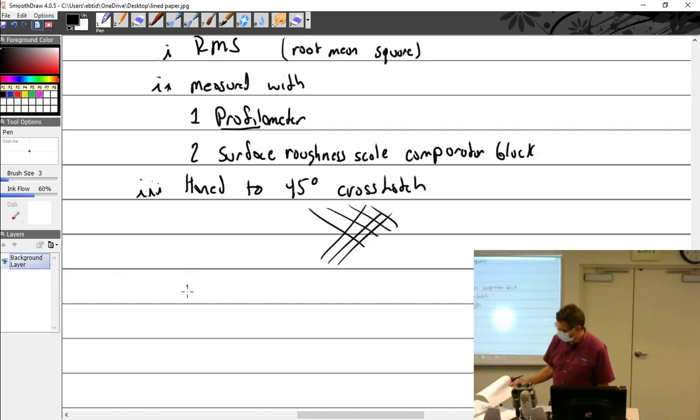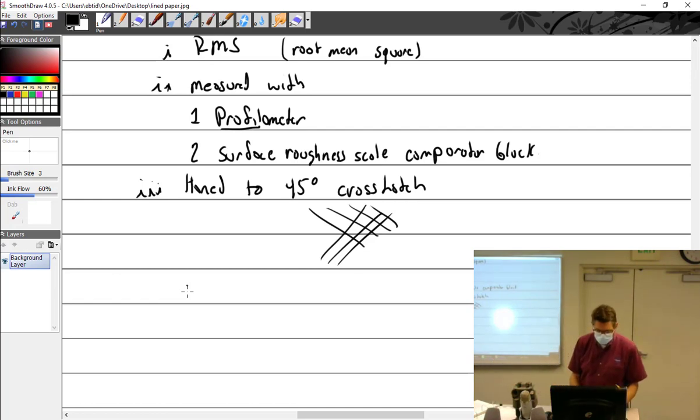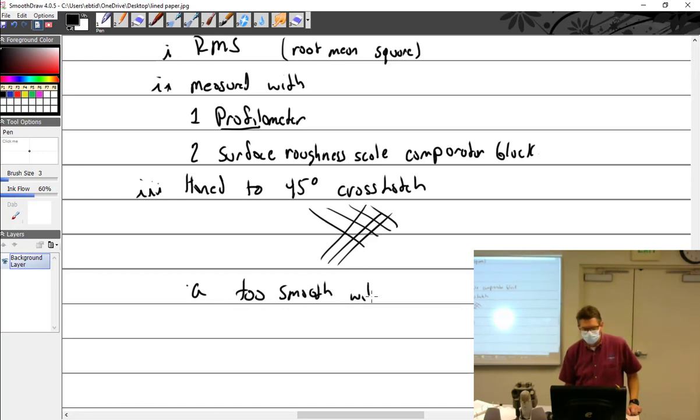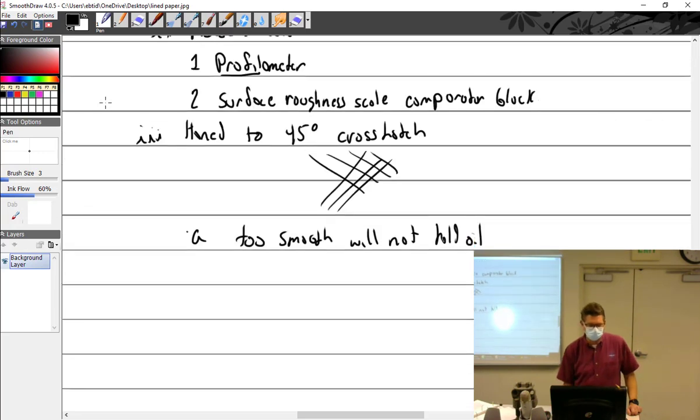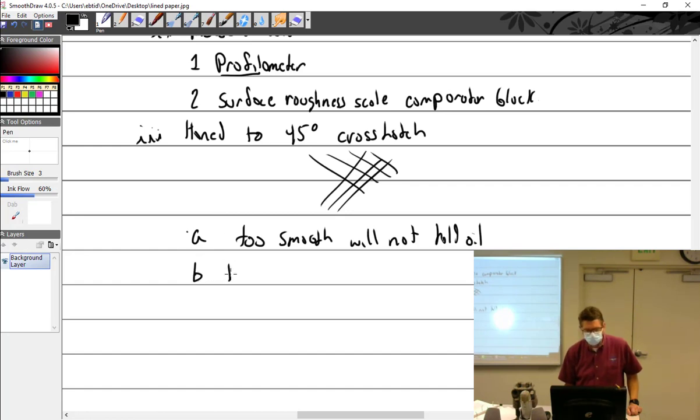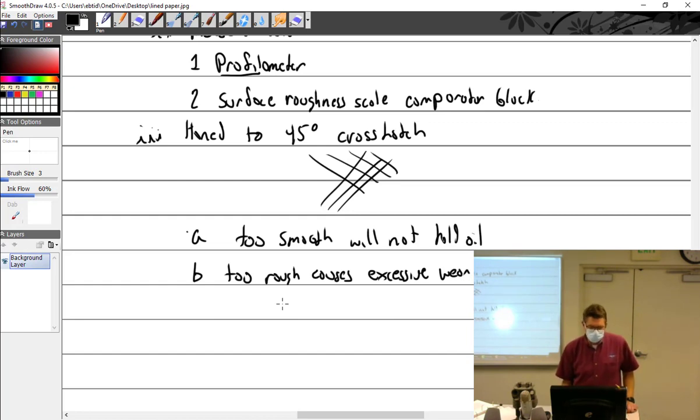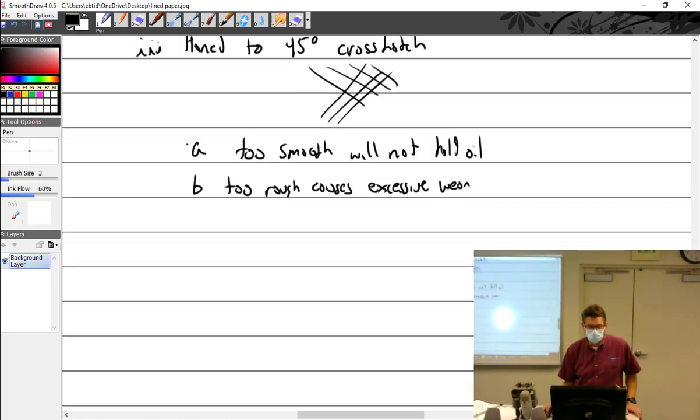It took me a while to work on that and actually get it right. Because if you don't, I can only imagine some people would just put it in, squeeze the trigger and kind of go around like that. And I see it sometimes when you take cylinders off, it's really flat. If it's too smooth, it will not hold oil. Too rough causes excessive wear.